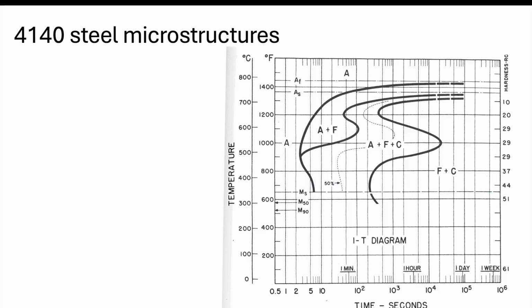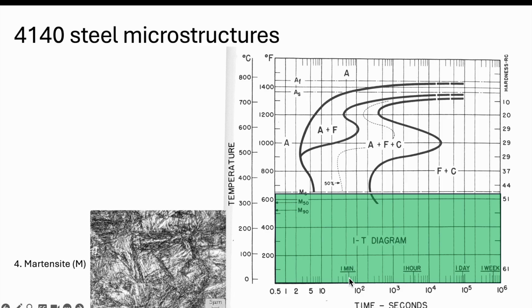And lastly, in this last band, the green band here at the bottom, at about 325 or less, this is where we see martensite. So again, martensite is that metastable phase, and it also has a very fine structure of this BCT metastable phase. Very fine structure, very much looking like needles.